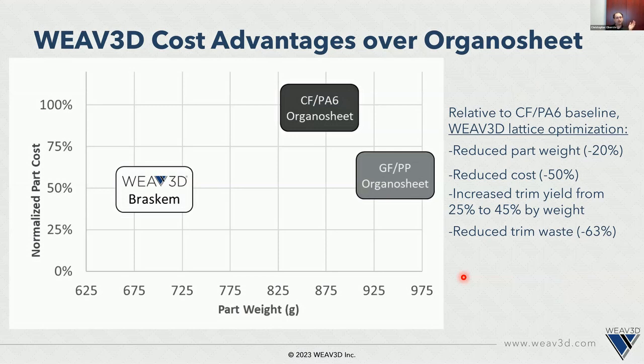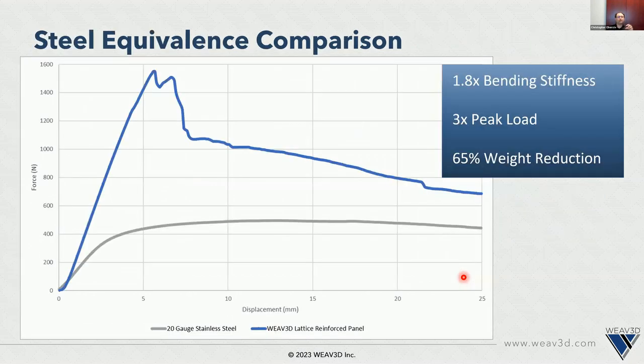The key thing though here is that we were able to improve the yield of this panel in terms of mass in versus mass out, from 25% in the organosheet to about 45% in our solution. And that resulted in about a 63% reduction in trim waste. So not only is this lighter and cheaper, but it's also a more sustainable solution in terms of reducing waste to landfill.